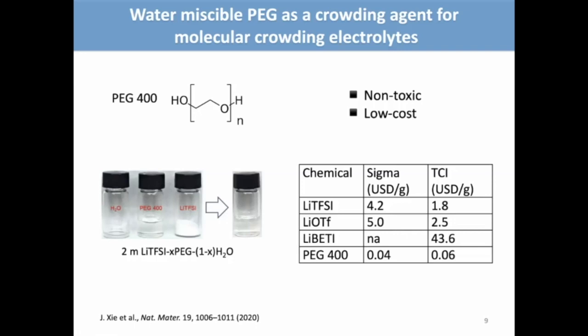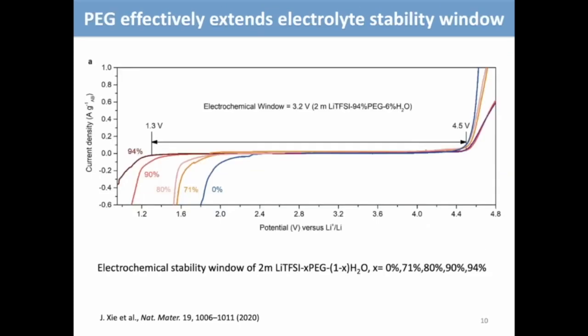In order to verify this concept, we found a very common crowding agent for water. This is polyethylene glycol, a water miscible polymer, which means that it can be mixed with water in any ratio. Thanks to that, we can make this type of electrolyte with more than 90% PEG mixed with water. And PEG is non-toxic and low cost. You can see this material is significantly lower in cost compared to the lithium salt. The electrolytes that we're going to use have only 2 molarity for the ion conduction, and we will vary the PEG content to see the stability window of water.